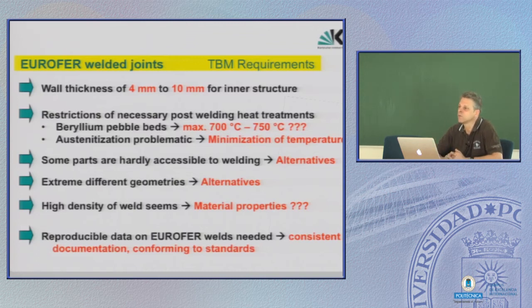And indeed with Eurofer, in almost all cases this is a perfect measure and works. But in the case of these breeding units, you have to remember that they are filled with beryllium pebbles as well as with lithium ceramics. And if they are filled with these pebbles and you have to close the boxes by a final weld line, then you cannot perform the full heat treatment anymore, because the beryllium pebbles cannot be heated higher than, let's say, 700 or maybe 750, but it's a delicate thing. You want them to be as cold as possible and probably not heated much more than 700 C.